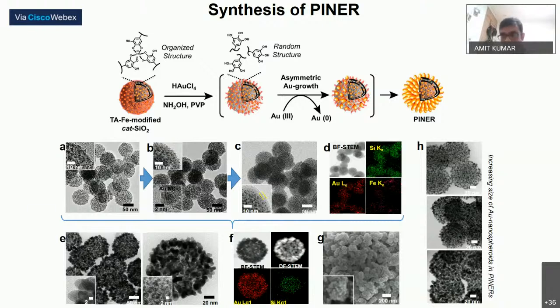We don't use any additional surfactant to synthesize such catalytic nanocrystals. After that, our intention was to selectively grow the outside nanocrystals into larger ones, which will turn into the plasmonic corona. For that, we coated this catalytic component with a very thin layer of metal-directing polymer. We took this tannic acid iron coordination polymer, which in the presence of gold chloride precursor disassembles and converts into random structures. These random structures guide and direct the metal growth into larger plasmonic structures, plasmonic petals, or nanospheroids.